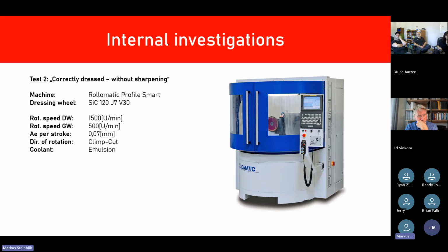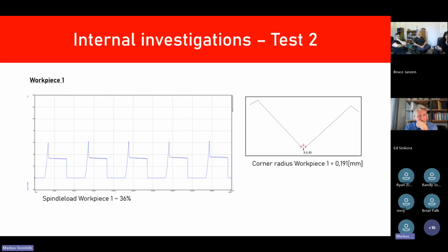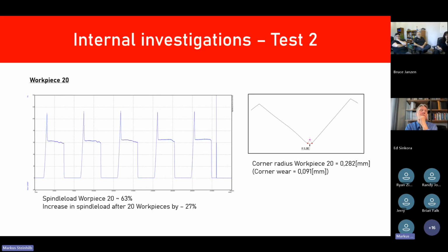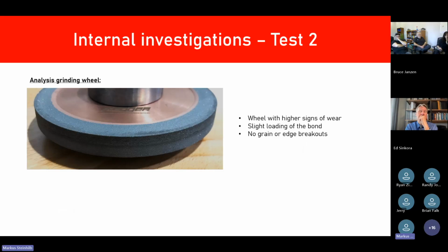The second test was dressed like the first one, but without the sharpening process. At the first workpiece, we can see right away that we start almost 10% higher than the sharpened condition. And we see a high peak at the first contact between the grinding wheel and the workpiece. After 20 workpieces, the spindle power increases by 27% to a total of 63%. The peak amplitude also increased. When we inspected the grinding wheel after the test, we noticed increasing signs of wear. There was slight loading of the bond, but no grain or edge breakouts are visible.